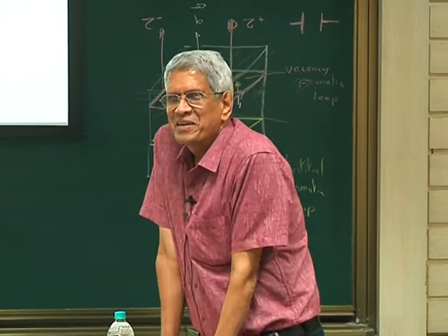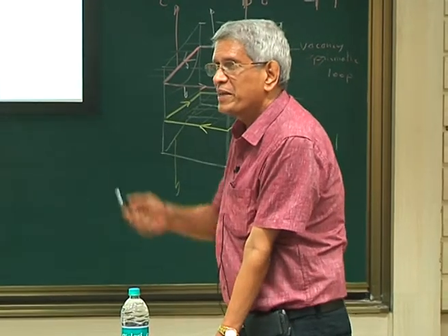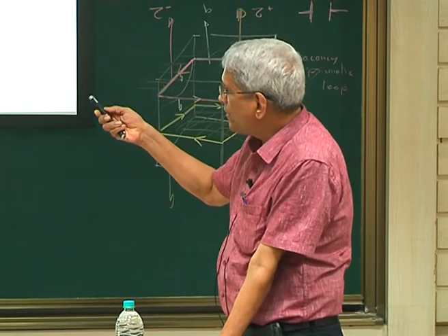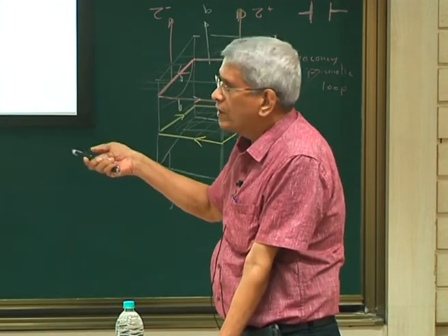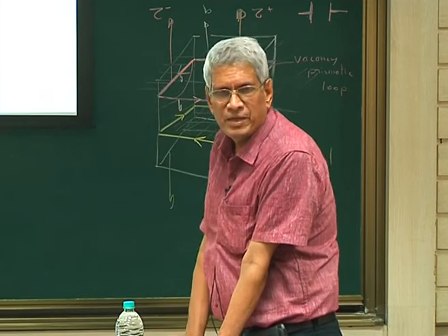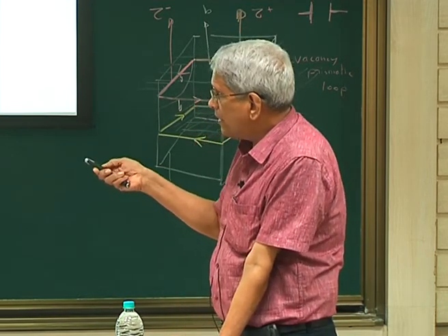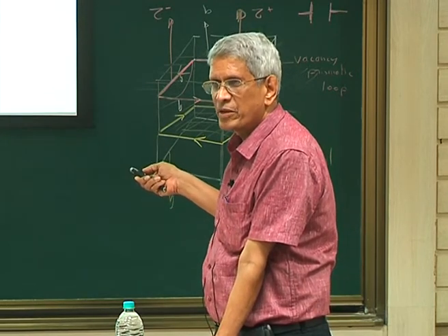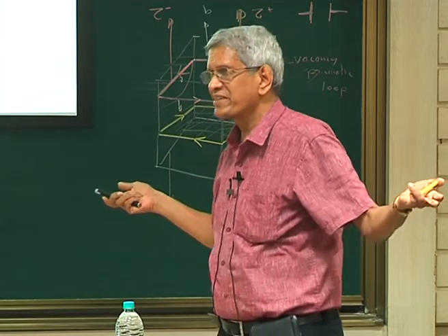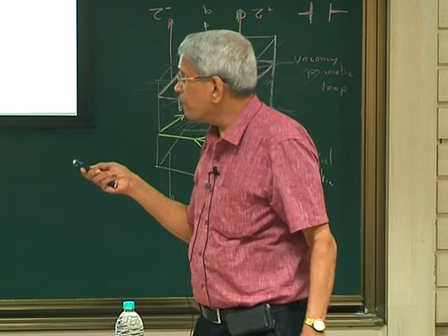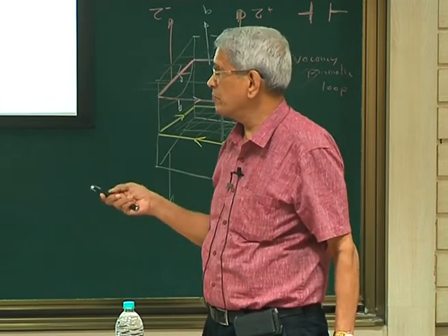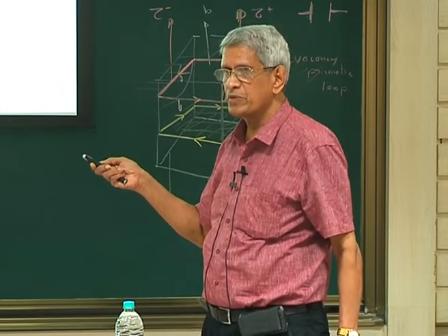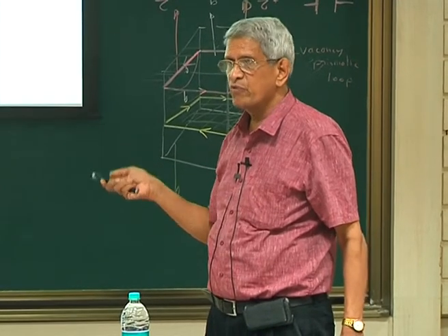So what is contrast? It is nothing but this: some quantity of the incident beam is entering the sample. Now, as that beam comes out, the amount of beam which is coming out in the same direction has some particular value. If that remains the same from all the regions, then there is no contrast, correct? If there is a variation, like in this sample, an amorphous material, this is what is going on. As the thickness changes, the amount of radiation which is absorbed changes.